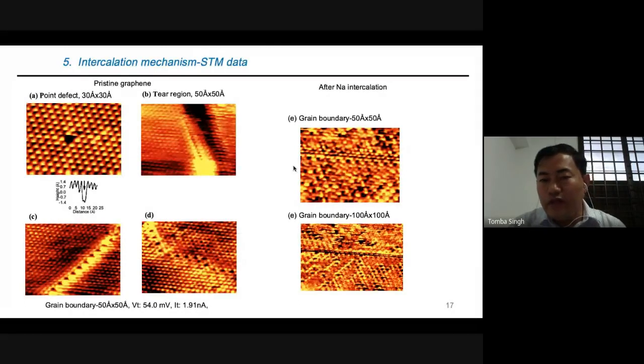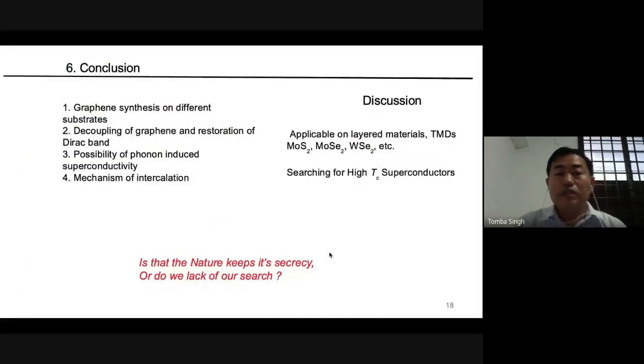To confirm it, we do low coverage of intercalated metal atoms, and we look for the grain boundaries or these defects. We found that deposition starts here. We see the intercalated regions near the cracks or boundaries. So we confirm the mechanism. Here, I would like to conclude the talk. I have discussed the synthesis of graphene on different metal substrates, and that graphene can be decoupled from the substrate to restore the pristine electronic structure or the pristine band gap. And we have discussed the possibility of phonon-mediated superconductivity in this system, and the mechanism of the intercalation also.